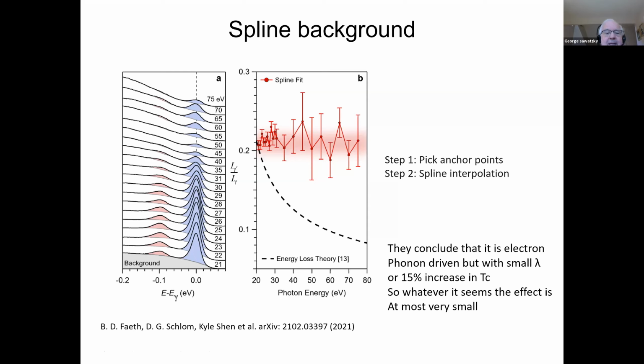That's a 60 millivolt peak. And if you change that spline background in that region just a little bit, then the intensity of this one will immediately increase by a lot. This spline always has to be a bit lower than what the experimental data shows because of the overlapping tails of these states that you have. So it really isn't correct to do this. However, they did it, and what they found, if they do it this way, is that it's constant. And that's exactly what you would have expected for intrinsic electron-phonon coupling. Okay, so let's just assume this is correct. I don't think it is, but we'll see.